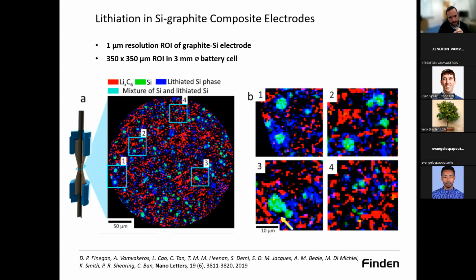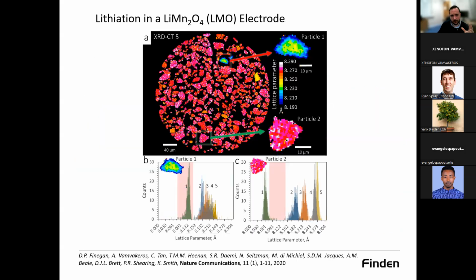silicon areas. And it's not just that you can do this for negative electrodes. This can also be done for positive electrodes. In this case, it was a lithium manganese oxide. This was also a dynamic experiment, and we were able to look at the individual particles and try to understand if there are heterogeneities in the degree of lithiation.